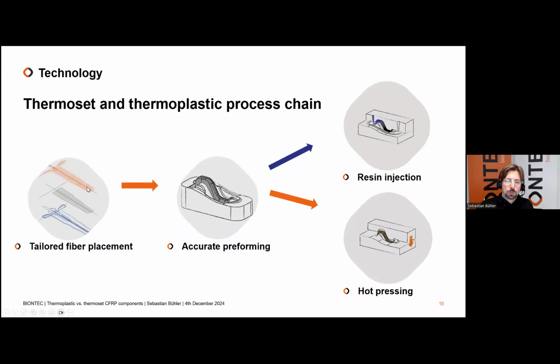If we go for the thermoplastic route, then our starting material is not a dry fiber. It is a commingled yarn. And again, it's the same way: load path aligned fibers. We can stitch several layers on top of each other again. The preforming step is quite the same compared to the thermoset way. And then with that preform, we go into hot pressing. I will show you later in more detail. Under pressure and high temperature, we can consolidate the final part. What is not shown on the picture, but you have seen on the foil where we have the impression of our production site, is that after that we do CNC machining.